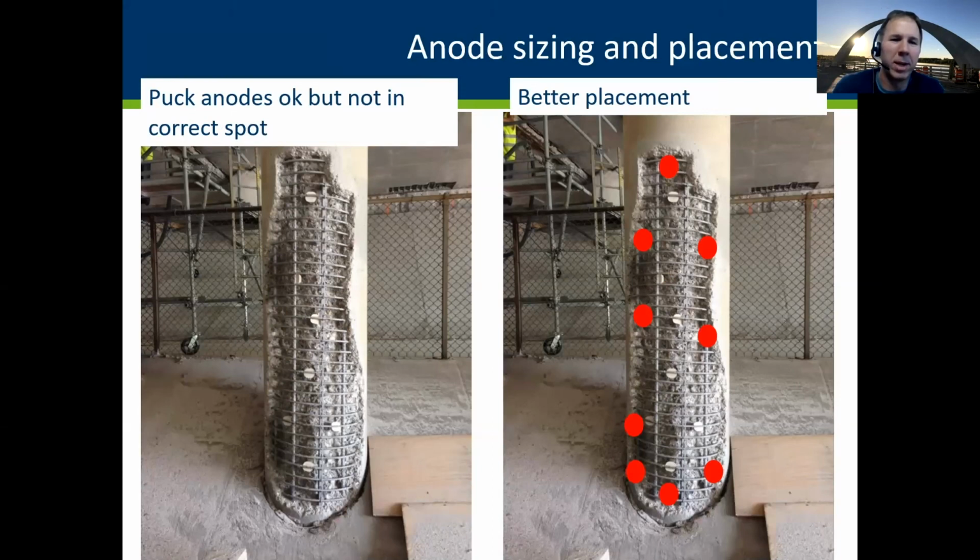So in the past, they chipped away this column that was in the splash zone for plows, and they're going to shotcrete this back. They threw in the anodes behind the steel, where they really aren't very effective. If you think of that radius of influence, the steel as it enters the old original concrete is where we want them. So they should have relocated these anodes to the exterior of your repair boundary. And the exact form of the column, whether it conforms to the true shape, we could bulge that out a little if we need to get the anode placed.